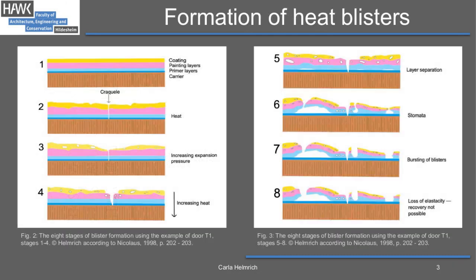The formation of heat blisters is shown in the two drawings at hand, as you can see. We have a normal paint setup on a wooden carrier, down here, the brownish layer, with layers of primer and paint, as well as a coating or varnish. Extreme heat causes thermoplastic softening of the varnish and paint layers. At temperatures above the softening point, the so-called pyrolysis starts. In this process, gases are developed that exert an extremely high expansion pressure on the strongly softened layers, and blisters form, as you can see, stages 2 and 3.